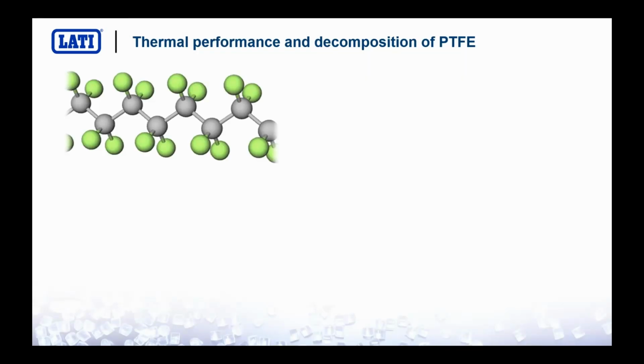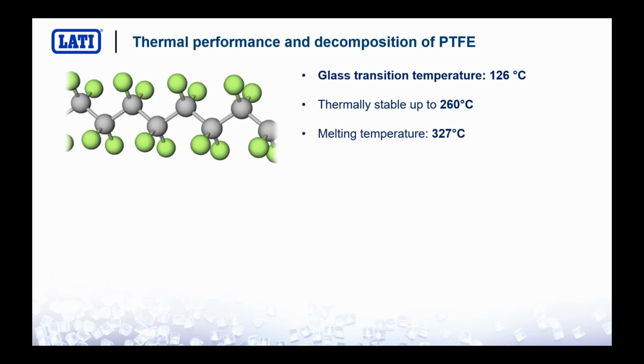Now let's come to the bad news. What happens when you heat up PTFE? I told you that the molecule is extremely stable. That's exactly the problem. PTFE has a glass transition temperature of 126 degrees C. It's stable up to 260. It should melt at 327, but actually it doesn't melt because of viscosity. But from 350 on, it starts thermal decomposition, and that's the problem. You have a full depolymerization above 650.